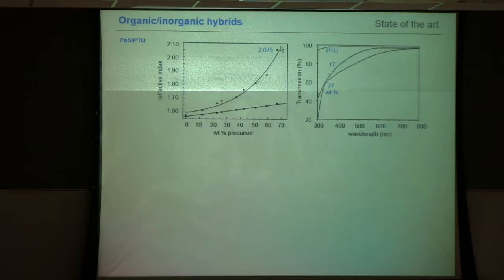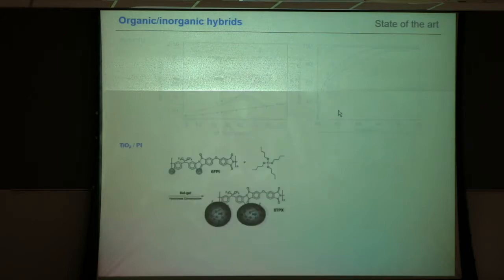However, the scattering now comes when you measure transmission. So here we just have the polythiourethane by itself, very good. But as soon as you add even a little of the lead sulfide particles, you see this tail coming up, which is simply scattering. So that means you can't use your material up to about 650 nanometer. And the more you add, you get unwanted absorption because of the particles. We want to have materials that are as transmissive as possible in the visible.